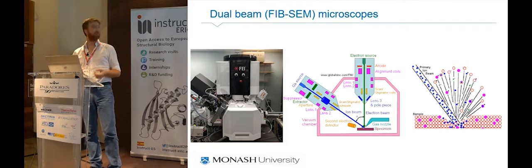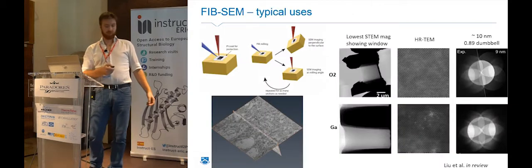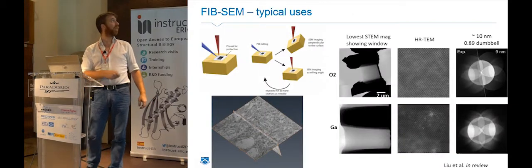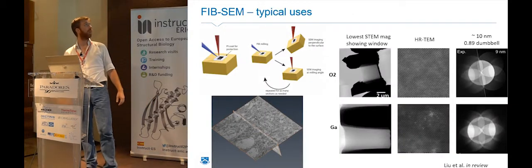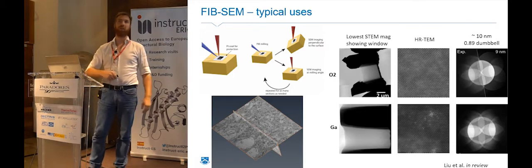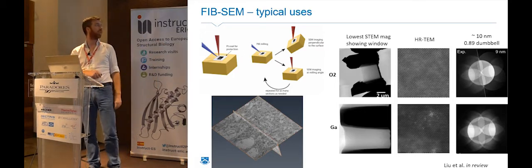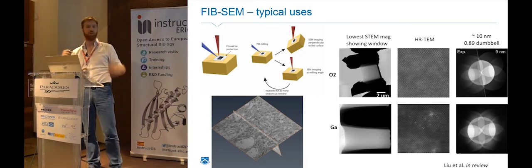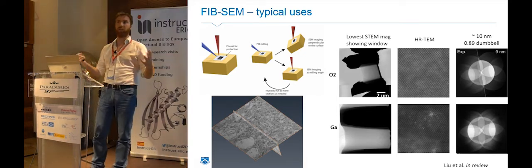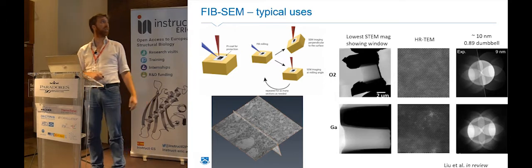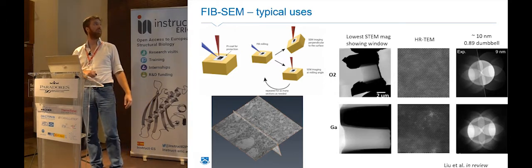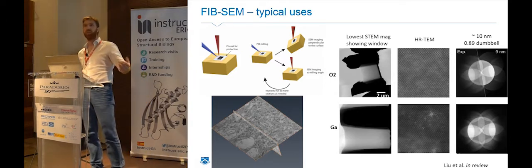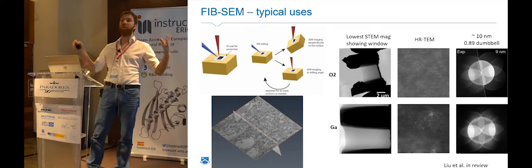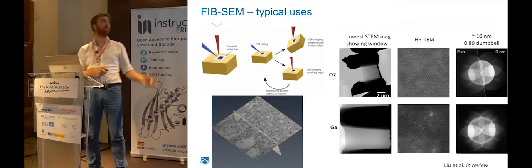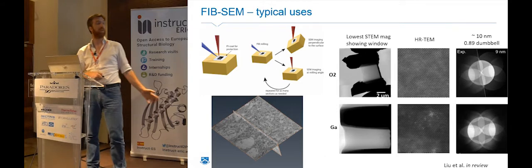So, what are the typical uses? Typical uses are FIB-SEM tomography. You image with the SEM, then you shave away the surface, then you image again, and so on and so on. This will provide you with a volume of all the electron densities in your sample. Another very common thing is to prepare samples for TEM. You have a sample which is too thick for transmission electron microscopy, so you thin it down, and then it will be compatible with TEM.